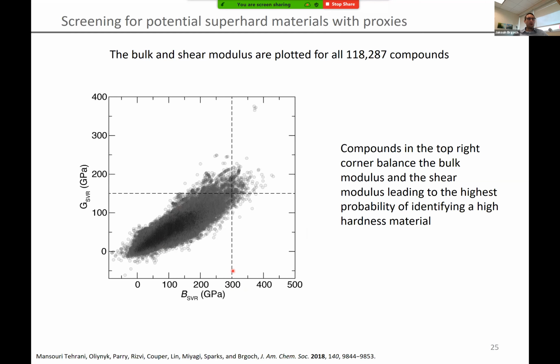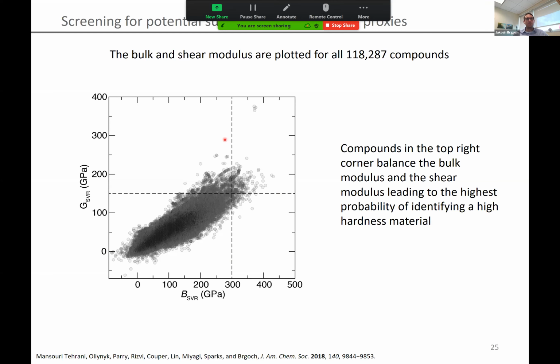We can put our bulk modulus, ultra incompressible cutoff line here, and we can put our dislocation motion shear resistance at 150 gigapascals here. We know that any new super hard materials are likely to fall in this region in the top right corner.